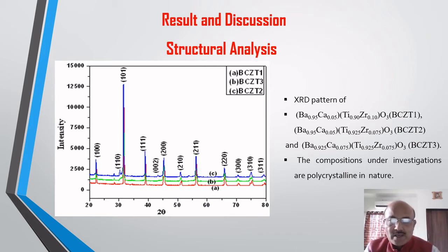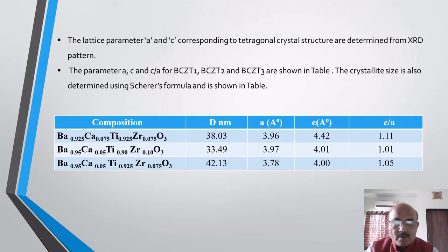This is the XRD graph for all compositions. From this graph, we observe that the compositions under investigation are polycrystalline in nature. By using the XRD pattern, the lattice parameters a and c corresponding to the tetragonal crystal structure are also determined. The parameters a, c, and c/a for BCZT1, BCZT2 and BCZT3 compositions are shown in the table. The crystallite size is also calculated by using Scherrer's formula, and it is also shown in this table.